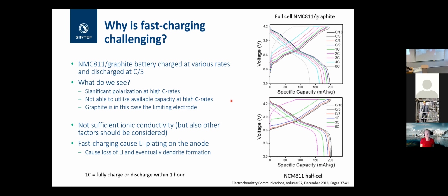So here just shows that because you have limiting ionic conductivity, you are also limiting the speed, how fast you can charge your battery. Another factor which you can't really see from these figures, but which is also important to think about for anyone that has an EV and wonders why you shouldn't be fast charging all the time. Fast charging can cause lithium plating on your anode. If you do that continuously, you will eventually form dendrites, which will short circuit your battery, and that's not good.